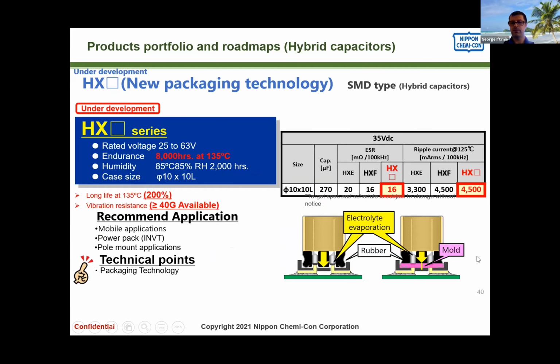The next thing I'm going to talk about, and there are only a couple more slides, is a new type of process that we're introducing. This slide is for hybrids. We also are planning to offer it for liquid electrolytic capacitors, and there's a two-pronged reason for that. One is, of course, longer life. We mentioned earlier about the electrolyte diffusing through the rubber and being, quote unquote, lost a little bit. I mentioned that most of it is consumed, but some of it is actually lost through diffusion, especially on thin rubber designs like surface mount. So anything we can do to decrease this amount of electrolyte diffusion will result in a longer life.